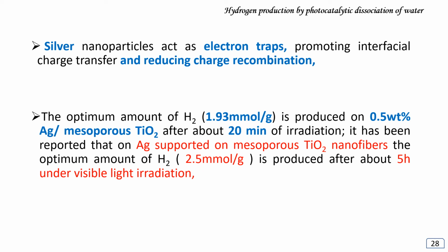The optimum amount of hydrogen, 1.93 millimole per gram, is produced on 0.5% Ag on mesoporous titania after about 20 minutes of irradiation. It has been reported that on Ag supported on mesoporous titania nanofibers, the optimum amount of hydrogen, 2.5 millimole per gram, is produced after about 5 hours under visible light irradiation.